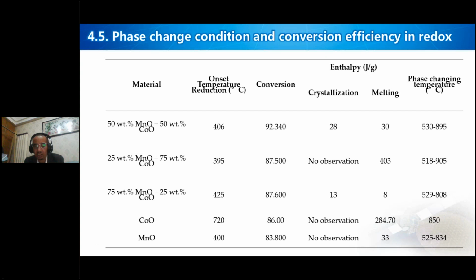So we also checked the phase change condition and conversion. Still, we checked the phase change condition and then the reduction temperature. The 50% still occurs on the reduction at 400, as we said before, and the conversion rate for this is 92.34, and the phase changing temperature is almost in this region. It has the melting, crystallization, and then this is the overall result during the experimental analysis. Still, we checked that this 50% is important in different aspects.